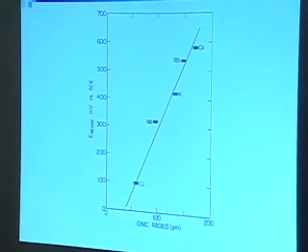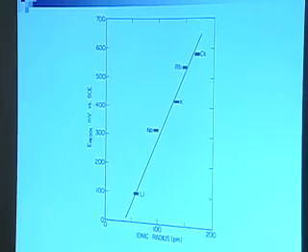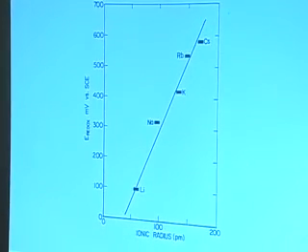OK, take those cyclic voltammograms and take those redox potentials that you measure from the half-wave potentials and plot them now versus the ionic radius of the cation. And you get an amazing linear relationship. Now, this was really astounding because what are those ions? Those are the spectator ions. They're not supposed to do a thing. And here, they're changing the redox potential over a little over a half a volt.